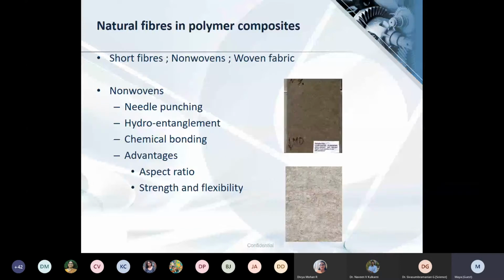Now, they can mainly be used in three forms: short fibers, non-wovens, or woven fabric. Non-wovens are made by three main techniques. Non-wovens are actually fiber mats, so there is no weaving, it's just a fiber mat, and the bonding is created by these three techniques. In needle punching, bonding is created by mechanical interlocking, because the fiber mat is passed through a conveyor belt and you have needles moving up and down the fiber mat. That creates mechanical interlocking and the bonding.